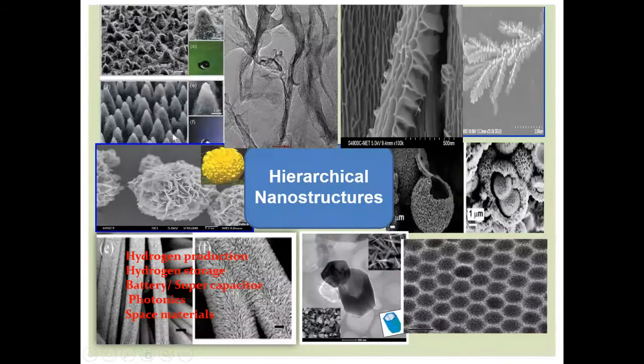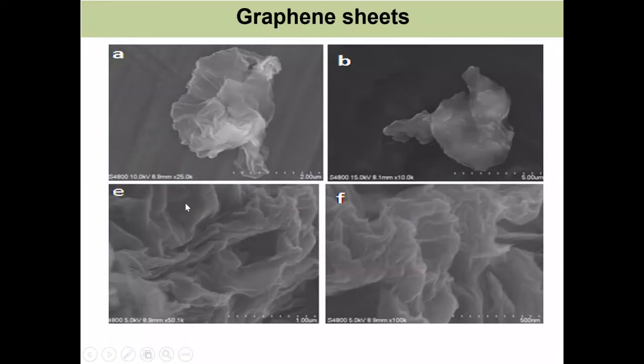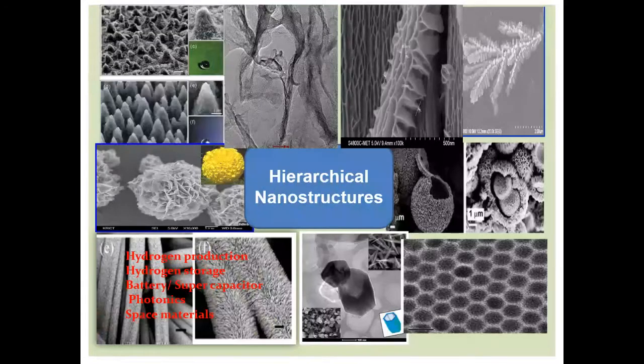See the structures of nanostructures we do. This is the graphene, then this is a very highly porous structure, honeycomb structures, then a flower-like structure, which is a porous structure again. Each petal is very thin, few nanometer scale, 1 nanometer, 2 nanometer scale. The porosity is so high, the aspect ratio is very high. A hairy kind of structure is required in sensors, we do it. And zinc oxide shows 3 shapes: rods, cups, and needles. All are because of the processing, how we synthesize.